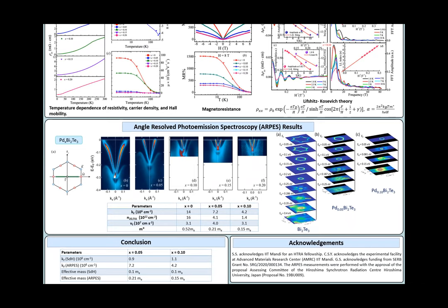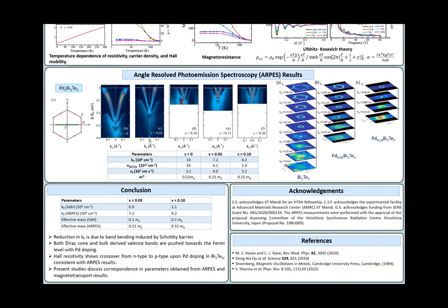depicts a narrow line width for bismuth telluride, and here we see the bulk valence band as well as the Dirac point energy shifts towards the Fermi level upon Pd doping. This is well in conformity with the Hall data that shows n to p type crossover upon palladium doping. Here we see the hexagonal warping effect decreases upon palladium doping and turns more circular. Therefore, taking together the SdH data and ARPES results, we see that there is a reduction in Fermi wave vector from SdH data, and this reduction is due to the band bending effect.